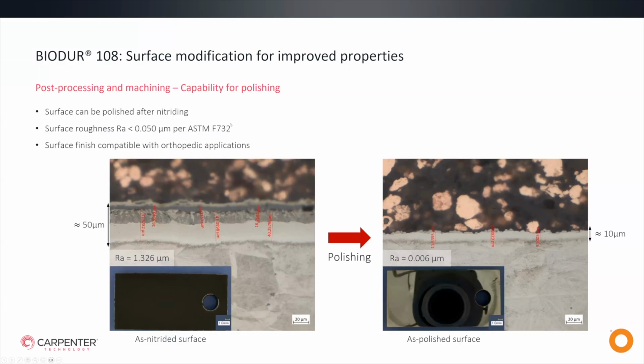So the patent that we provided, right, the approach that we took combines nitriding with controlled polishing and machining, really so that we could ensure the nitriding layer remains compressive and it doesn't introduce harmful tensile stresses, areas that are inconsistent in the surface that could potentially drive cracking.